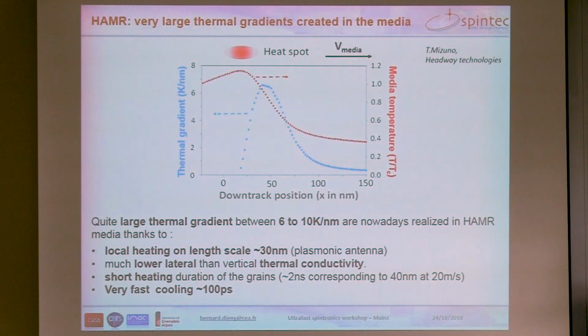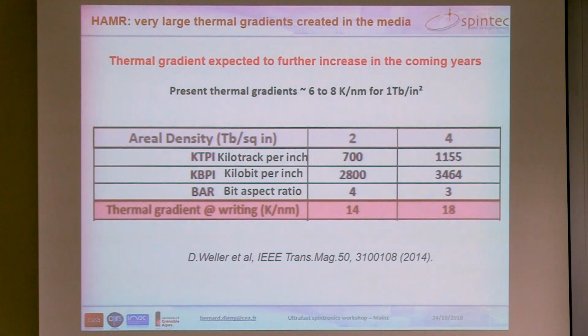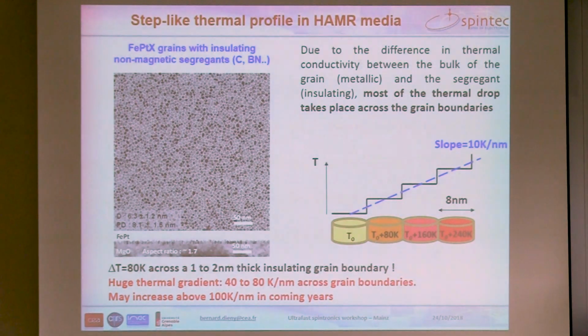But I'm coming to this because this is actually an average thermal gradient along the media. In the future, when the areal density increases to 2 or 4 terabit per square inch, it is expected that the thermal gradient will have to be increased to 14 or 18 Kelvin per nanometer. But this is the longitudinal average thermal gradient.